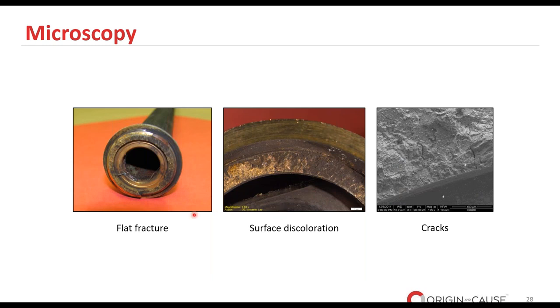So having said that, let's take a look at the fracture surface again and we see our telltale signs of SCC: the flat fracture, indicating little to no deformation of the material before it fractured. The surface discoloration stands out, and importantly, the presence of microcracks. These are strong indicators of SCC as well. And I need to stress here once more that stress corrosion cracking isn't something that can be confirmed with a visual examination just with the naked eye. More advanced techniques and metallurgical evaluation are always needed to confirm the case. And in my opinion, electron microscopy is something that always helps and is necessary.